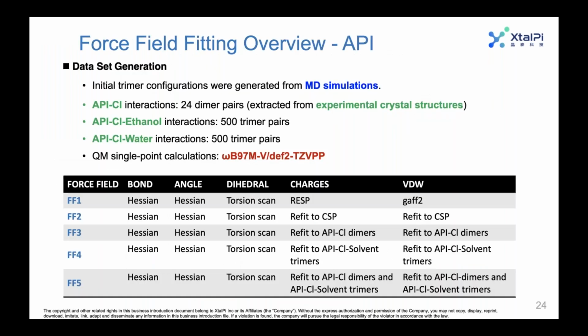The next thing I want to explain is the force field fitting. So the first thing to do was to tailor make a force field for the crystal itself. There was an additional challenge that metformin HCl is a salt. So we had to consider that as well during the force field parameterization. So in doing that, we looked at the API and chloride interactions. We also looked at the salt and ethanol interactions and salt and water interactions. And taking all this into consideration, we trained 5 different force fields, and those were refit with various interactions that we obtained up here.